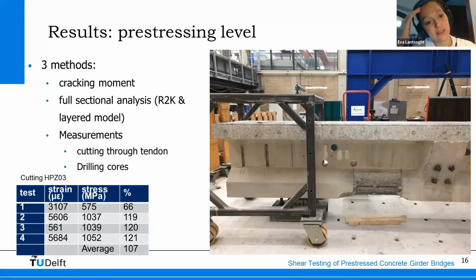For the third girder, we found with cutting of the wire, we cut 4 wires, and we had quite some difference in the results, right? You see that they range between 66% and 121%. And essentially with all the measurement techniques that we used to define the pre-stressing level, we found a large variation in the results. We actually found that using the sectional analysis seemed to be a more reliable method.